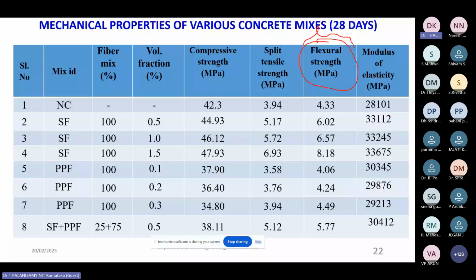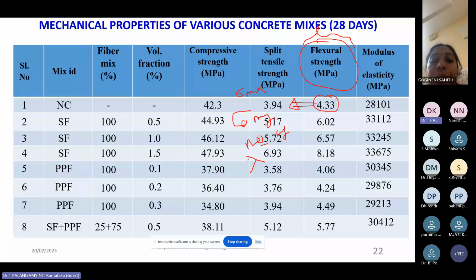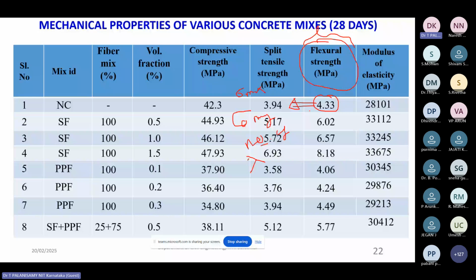For example, for normal concrete, I have a flexural strength of 4.33. From this, I can fix my sigma max and sigma minimum, and the number of cycles or frequency. Frequency I can fix. For example, I can take 4.33 and use a maximum stress level of around 90 percent, 0.9 times 4.33, which is 3.89. I can use 0.9 times sigma. This is the sigma max.